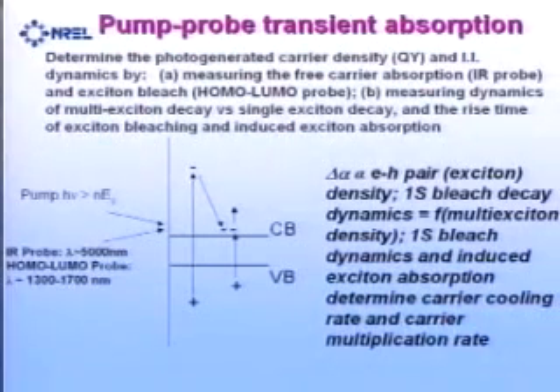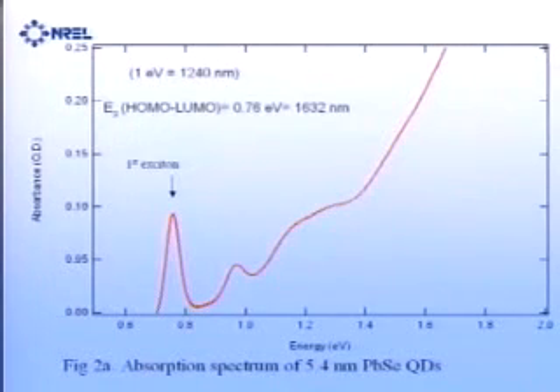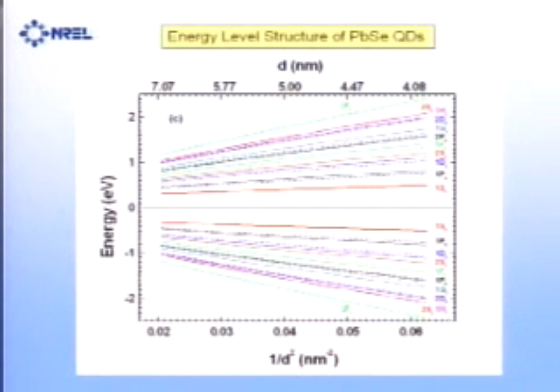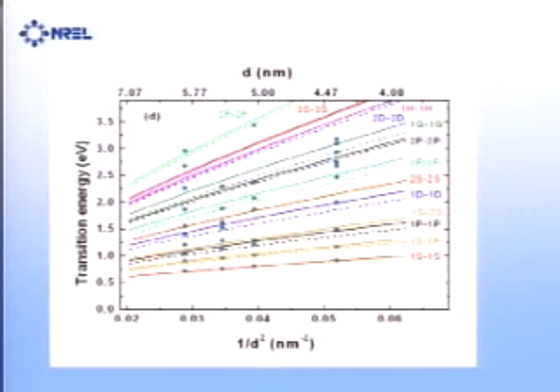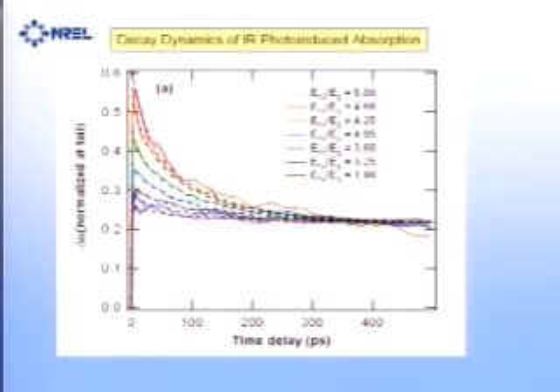So what's important here is to do the time-resolved dynamics, which is done by luminescence or transient absorption. I'll just run through this. This is just the theoretical energy levels as a function of 1 over the size of the quantum dot squared, showing this fan-like structure due to the quantization. Our experimental absorption data match this theoretical picture pretty well. The critical data is looking at the longer time decay of the carriers once they're created as a function of the photon energy. And it's expressed as the ratio of the photon energy to the band gap. So as we go from 1.9 to 5, we get this increase in the